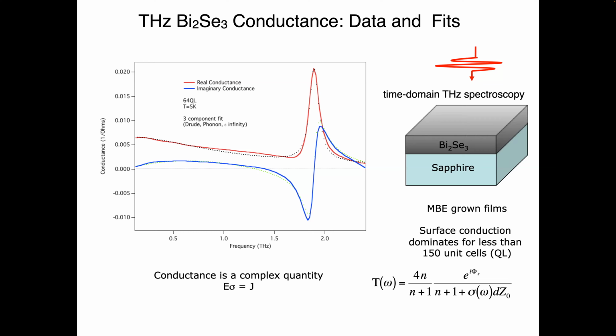We measure something that's called the complex transmission function. This is the transmission function. It tells us the amplitude and the phase of the light that's transmitted through, and it's due to the complex conductivity that's down here, right? So we measure that, and we just invert this in a simple way, and we can get that. And when we do that, that's what you get.